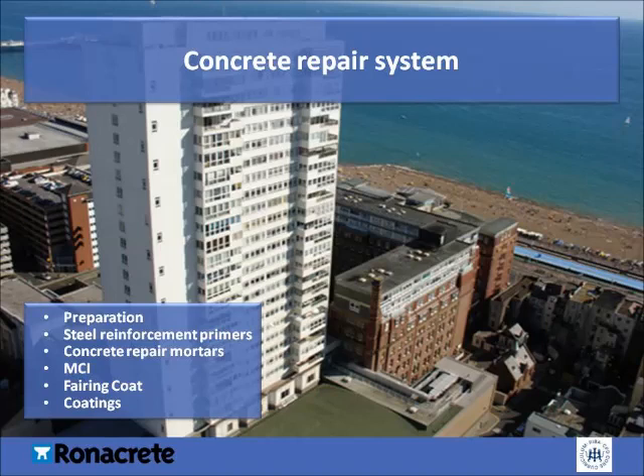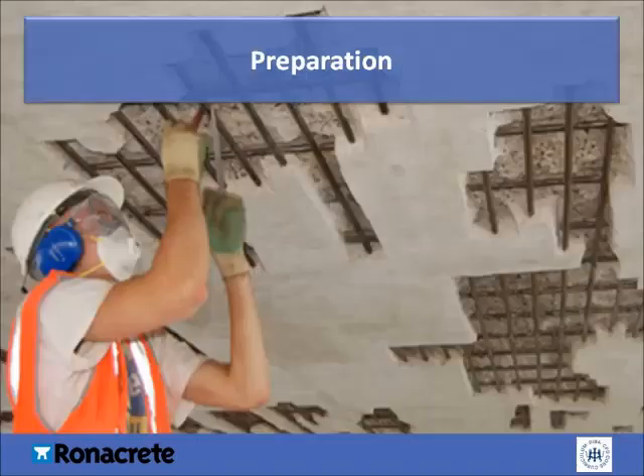Now let's look at the steps and materials involved in repairing defective concrete following diagnosis. As with many concrete repair projects, the key to a successful outcome is in the preparation. Key techniques include: removal of algae, usually with a proprietary algae remover; grit blasting of the concrete surface and reinforcing steel, though this may not be necessary when using polymer mortars; needle gunning to remove defective concrete; sawing edges at repair perimeters to avoid feather edging of repair material; and wire brushing of reinforcement if required.